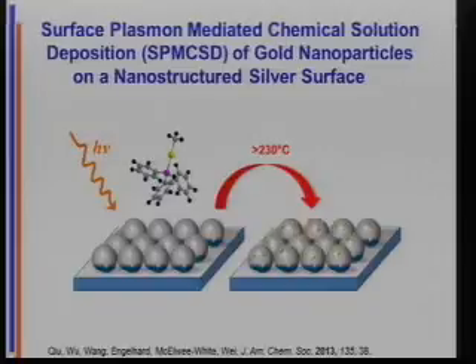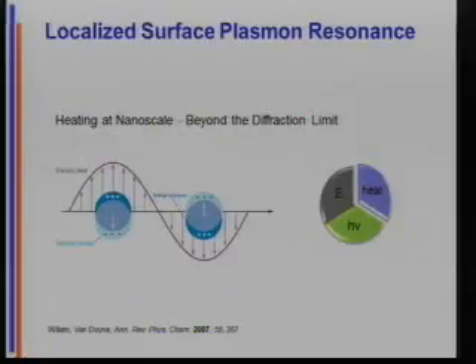He said, we can make these substrates. These are silica balls, and they have silver sputtered onto the top of them. These are nanoscale things. They give a really strong surface plasmon resonance response, and I would like to use that as a driving force to grow material. And because I'm a physical organic chemist, I said, what's surface plasmon resonance? That's where a lot of my projects start, like, what's that?